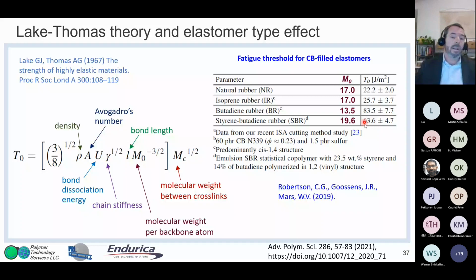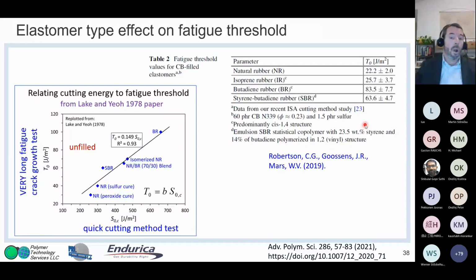And that's exactly what the classic work of Lake and Yeoh showed on unfilled elastomers. So our work was on carbon black filled elastomers, and their work was using unfilled elastomers. But again, butadiene rubber is the highest, natural rubber is the lowest, and then SBR is in between. And you can always blend elastomers too, right, and get something in the middle.